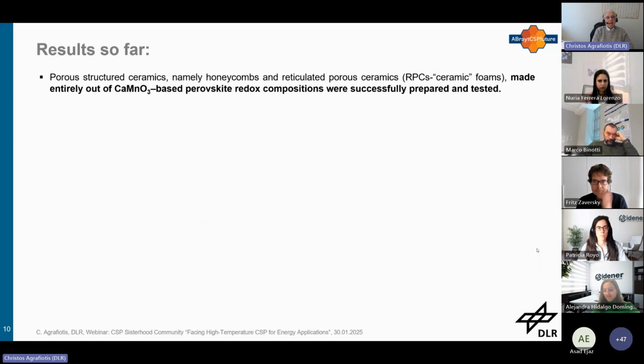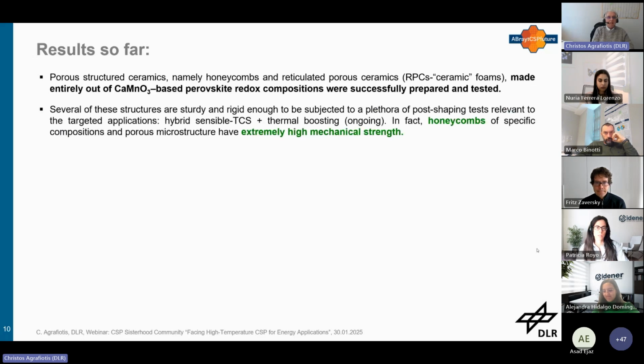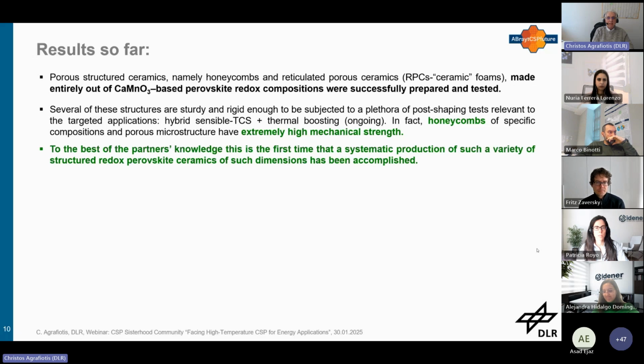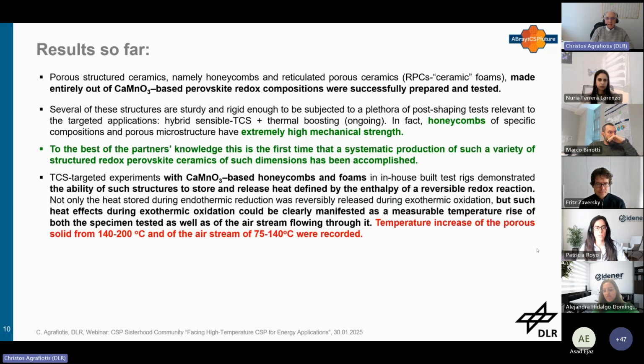So far we were able to synthesize porous structure ceramics made 100% out of perovskites. These are robust enough, and we can use them later on for mechanical testing and any other tests. So they have good mechanical properties. We believe that this is the first time that such a systematic production of such structures has been reported. And also the basic thing is that we demonstrated the proof of concept with this material.